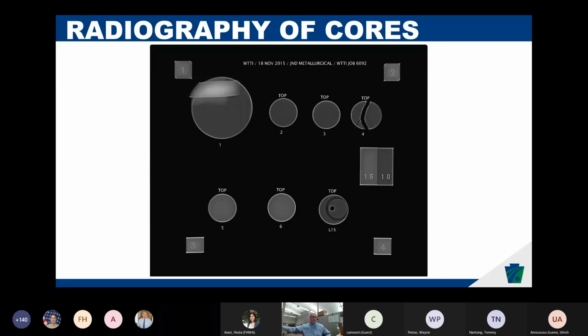So for some of the fatigue cracking that we have, obviously a mitigation measure is crack arrest holes. Normally you drill crack arrest holes and perform some type of mag particle inspection to ensure that it was fully drilled out, which is reassuring enough. But there's certain cases where they're tight fit areas, you can't really get some type of mag yoke in there, or it's difficult to drill out. So we will apply that reassurance and also add in radiography of those holes to make sure that we caught the crack. We fully removed the crack.